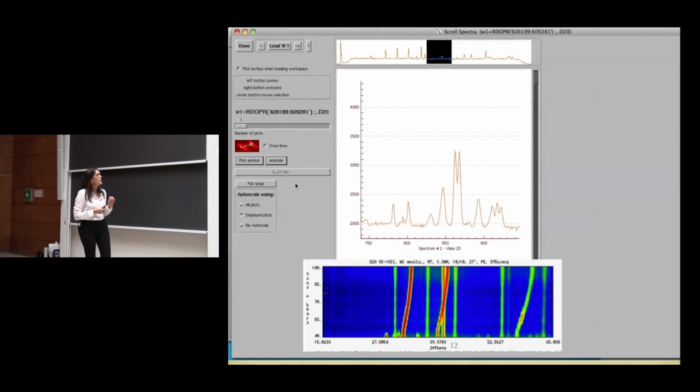And then here, what I'm going to show you is a typical neutron scattering experiment. And what we are looking at is angle and intensity. And this is what we call the Bragg reflections. So we have some structure, right? We have this periodicity, so we have elements that are going to repeat. And because they repeat, there is a constructive interference. And then we observe these reflections. We can analyze this data using Bragg's law and some other programs that we have to analyze, and we come up with a structure.